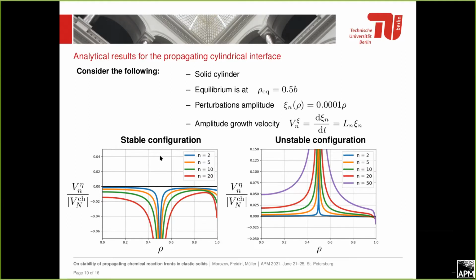As we see, at the 0.5 we have infinity, just because the velocity of the propagating interface is 0 at the equilibrium radius. But we see that for the stable configuration, at every point of our solution, these Ln are negative. So that means that our interface is stable.